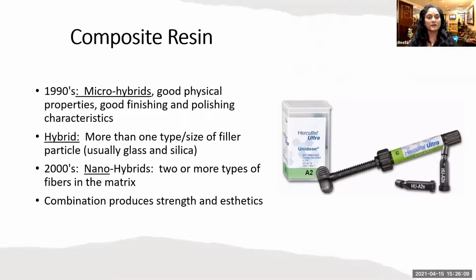And the hybrid aspect of this has to do with more than one type and size of filler particles. And they're usually made of glass and silica. Shift forward again another 10 years and we're looking at nanohybrids in the 2000s. So now we're looking at 2 or more types of fibers in the matrix. So in an ideal world, with a nanohybrid, you're looking at multiple sizes of particles in the filler and multiple types of filaments within the matrix, and you're looking at a very strong composite. And you are also looking at something that holds up beautifully aesthetically. So Herculite Ultra, which is what you're looking at here, is nanohybrid technology. This is what we use, and to boot, it is radiopaque. So when you place these, you can see these on x-rays.